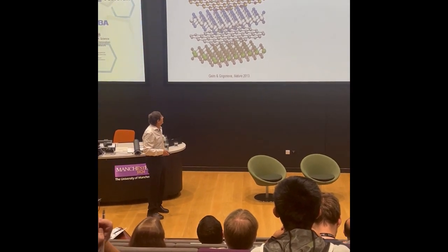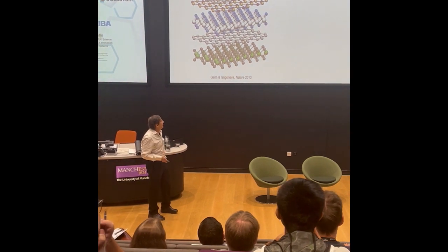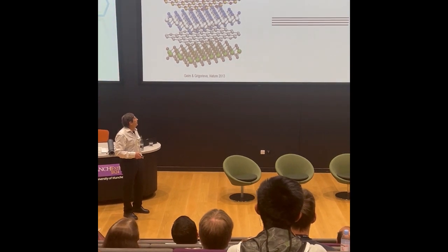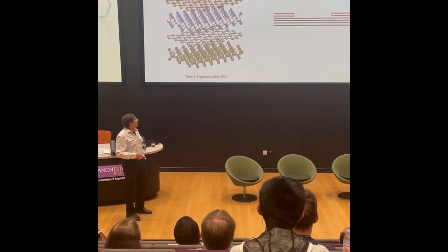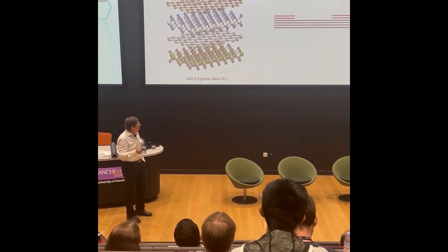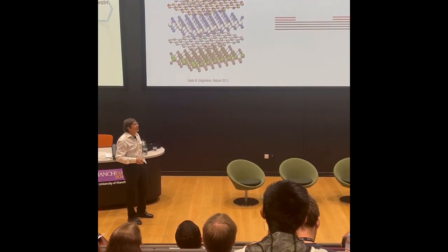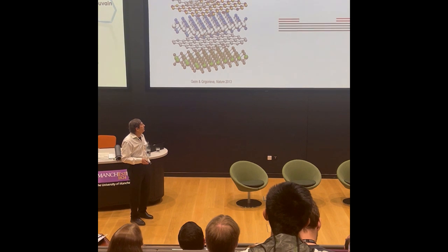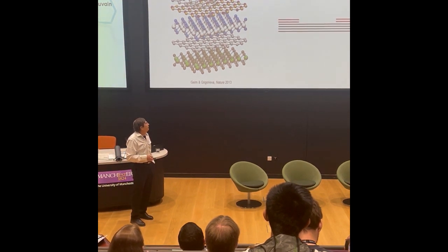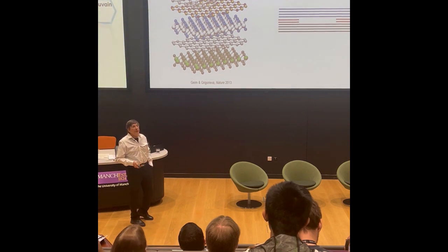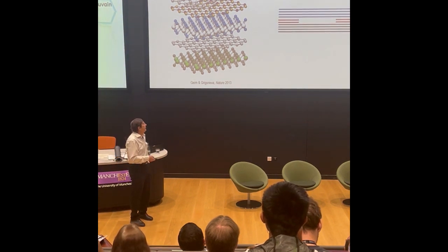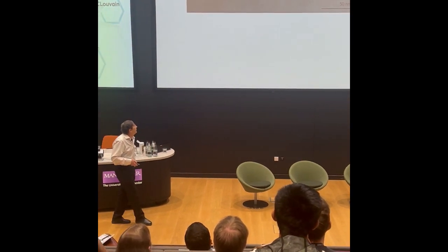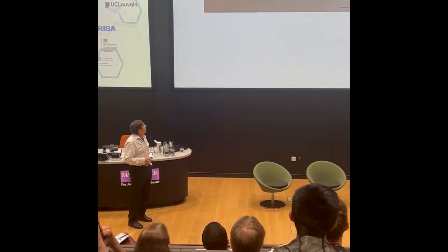Probably some immediately start thinking about the technique of van der Waals assembly, which is very familiar to this audience. You get an atomically flat two-dimensional crystal or flat surface, clean graphite. For example, one puts 1, 2, 3 layers of another material, whatever you want, it could be boron nitride or molybdenum disulfide, and closes it with a material of your choice. So that's a cartoon, but we managed to make these channels in reality.